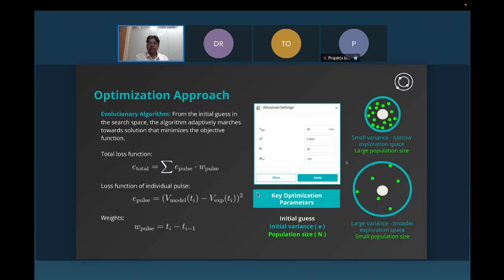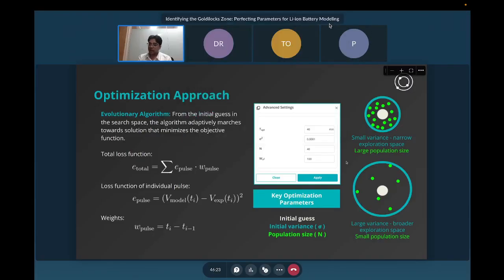Now, let me get into a little bit of details on the optimization approach that we have at OJA for the parameter optimizations. In this case, we are focusing on five of these parameters: the internal resistance, lumped resistance of the cell, two reaction rate constants on the electrode surfaces, and two diffusion constants. Now, that gives a set of five parameters, and as you would know, the more number of parameters you have for the optimization, the process becomes very complex and also challenging. And making sure that we have uniquely identified these parameters is a big challenge.